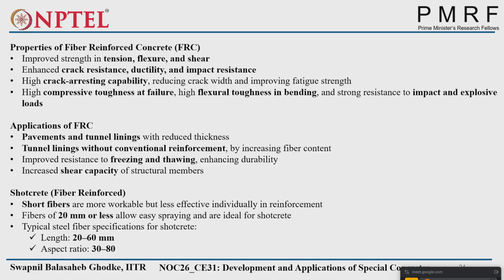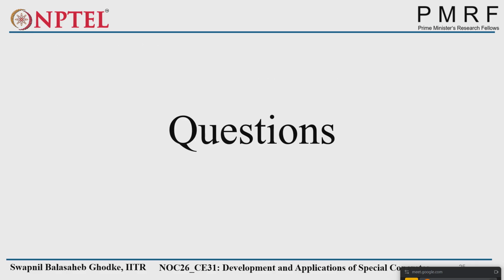It is also used in shotcrete, but as we have to spray the concrete, we always use small length of fibers. That is called short fibers, more workable but less effective individually in reinforcement. Fibers of 20 mm or less are generally used. Length will be 20 to 60, and aspect ratio of 30 to 80. So this is the brief overview of week 6, that is mostly about fiber reinforced concrete and a short introduction about the rheology.